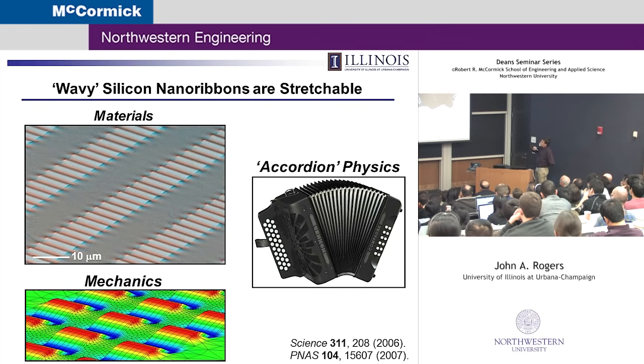If you take this very thin silicon, you can start with a membrane, cut it into strips, and now bond it to a rubber substrate. Ultimately, you want an elastic circuit. You probably need to use an elastic substrate. We like silicone rubber for that because we have interface chemistries that allow rigid and robust bonding to oxide surfaces, such as native oxide on silicon. If you take those silicon ribbons now and you bond them not just to a piece of silicone rubber, but one that's pre-stretched,